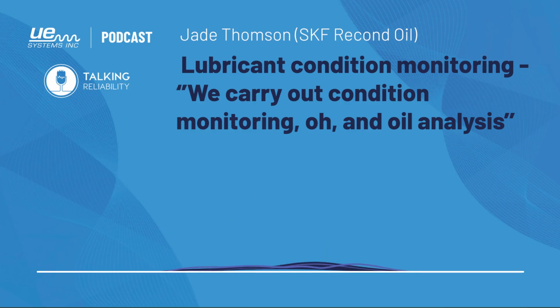So we'd not caught this before the failure because the customer had come to us after we'd had the catastrophic failure. So what this is showing us on the left is we've got every single wear mode possible in place here and occurring. So we've got a lot of adhesive and abrasive wear. So we couldn't really go back with a root cause to the customer. But what it did show is, one, they should be doing routine oil analysis, but it did show them the types of wear that had occurred up to that failure. We just couldn't root cause it down to one.